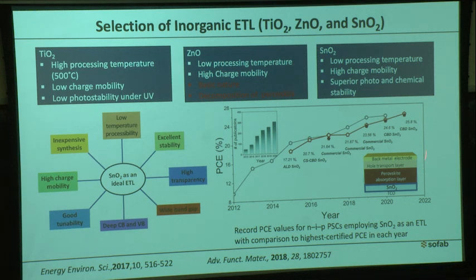If you look at this chart, we can see the popularity of tin oxide. The power conversion efficiency of tin oxide-based devices increased over the years, and already the power conversion efficiency has surpassed 20%. This is a little older data, showing about 25%, but it has already surpassed 26%.